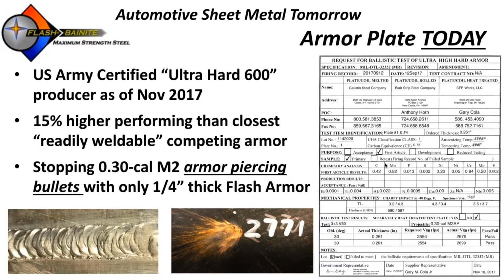Well, what we've done is we've worked with University of Tennessee, Knoxville, and Oak Ridge National Lab and gone through some trials and tribulations. And we have been able to get our ultra hard 600 with a rather simple welding process to have a non-brittle heat affected zone. What I mean by that is through the entire HAZ, the hardness is actually about 100 points Brinell lower than the ultra hard 600 itself. So that's a good thing for non-brittle failure. We've given an example of the weld on the left-hand side, lower.